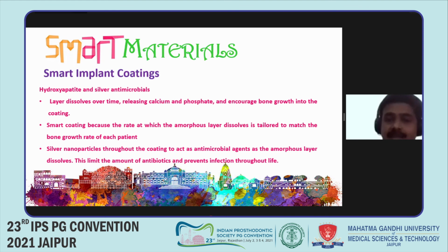So what they say is, why do you need this particular dissolution to occur? This dissolution occurs in response to that of bone which is growing. And the dissolution is specifically controlled by what we call the local acidity which exists. In response to an infection or an inflammation, we know that the acidity goes up. That is, we have a more acidic environment, the pH reduces, and therefore in response to this, the smart coating releases the antimicrobials.